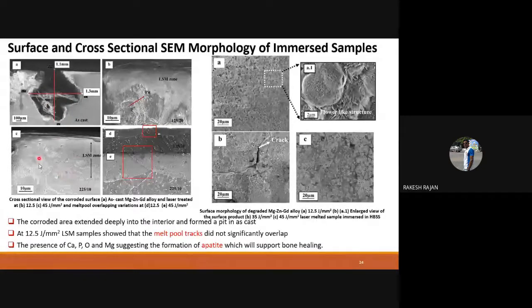In this case, even after 180 hours of immersion, the region is unaffected, meaning the degradation is very less. Here you can see clustered flower-like structures formed in the same microstructure, indicating apatite formation. In image A, there's a very dense formation of products - these white colors indicate dense product formation, showing that magnesium hydroxides are formed very effectively and stop further degradation.